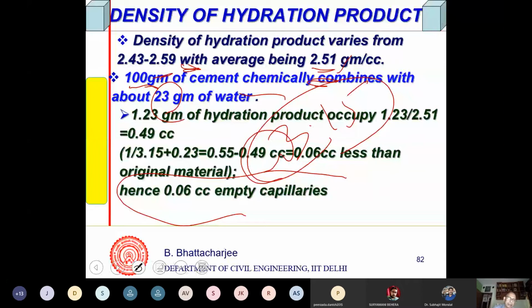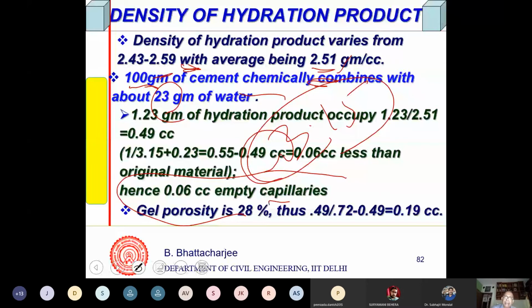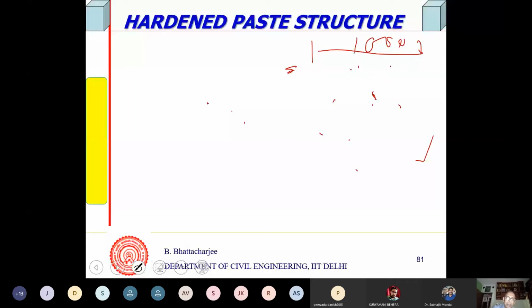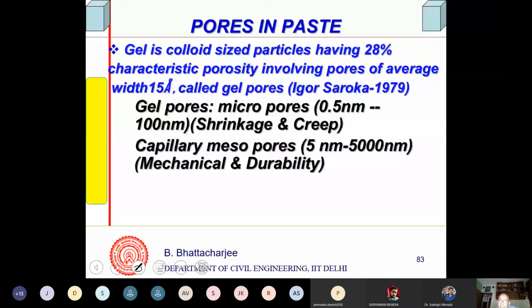Those are called empty capillaries. And this solid product which is formed has again got some pores inside, like the gel pores that we have seen earlier. So 2.51 is actually only solid, but 28% is still pores inside. So the actual solids have a specific gravity of 1.78 or so. This can be schematically explained like this. Gel is colloid sized particle having 28% characteristic porosity, which has been found out by BET kind of test.